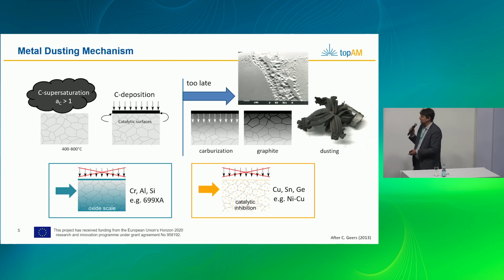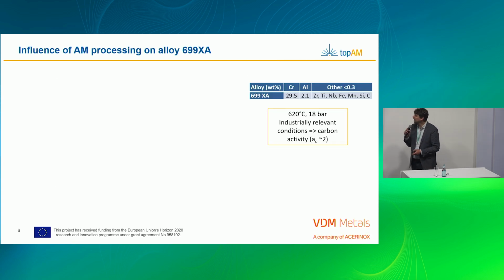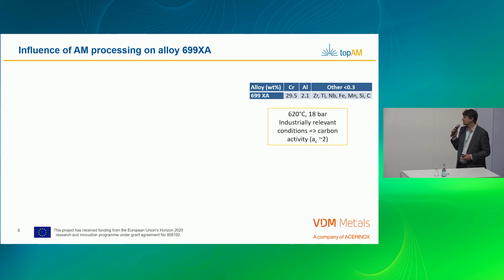The two approaches usually taken are to form a barrier on your surface to protect the material from these gases, or to have a catalytic inhibition of the carbon uptake. For that, this alloy was developed, which has an extremely high chromium content, as you can see, 29.5%, with some aluminum and some other additions for these particular environments. Today it's not only about this particular alloy, but the takeaways are applicable to all nickel-based alloys that are printed and meant for high temperatures.